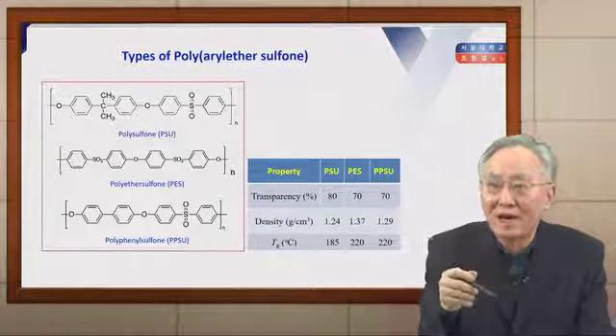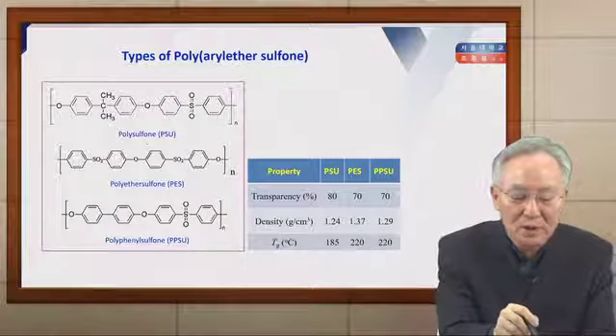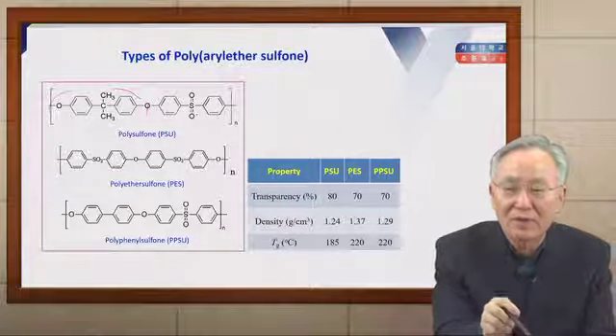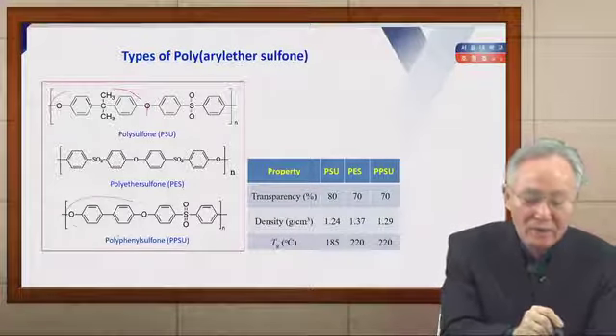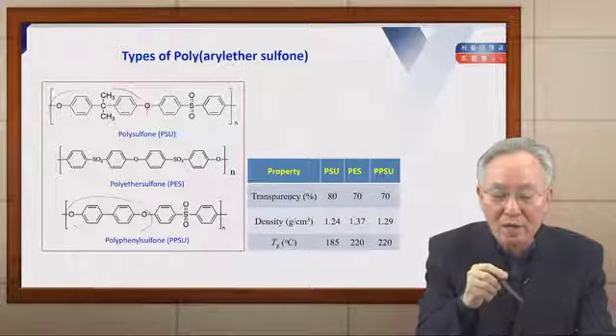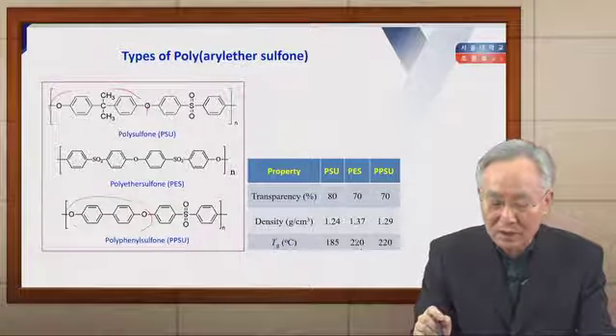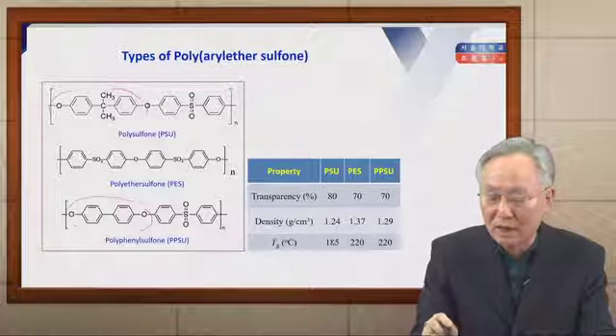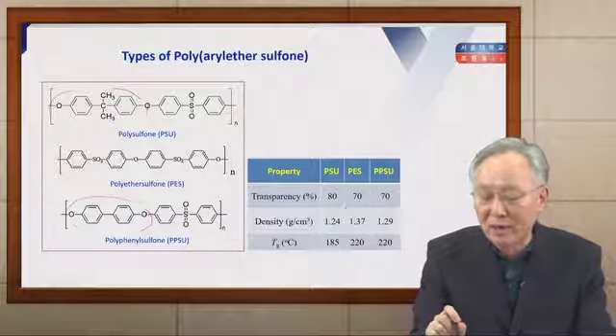There are several types of polyaryl ether sulfone. Polyethersulfone (PES) has a Tg of 220°C. Polysulfone (PSU) is synthesized from bisphenol A reacted with dichlorodiphenyl sulfone, and has a slightly lower Tg than PES. However, the transparency of PSU is higher than that of polyethersulfone, which is important for practical applications.